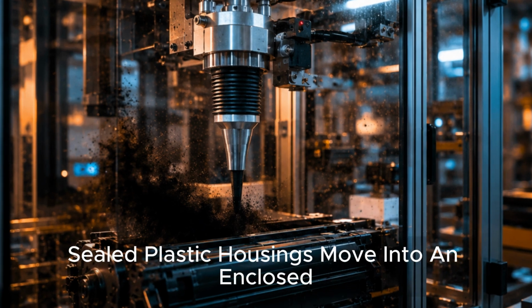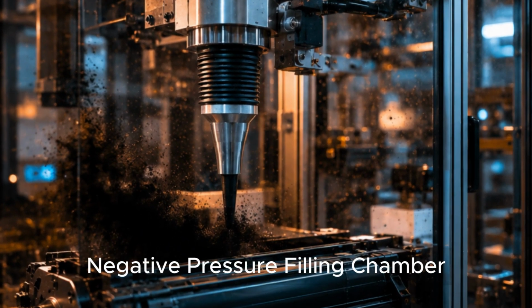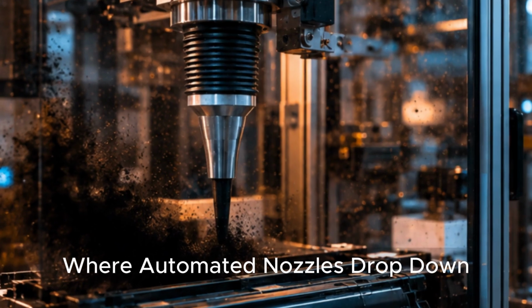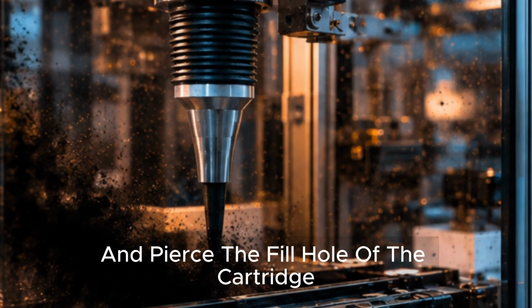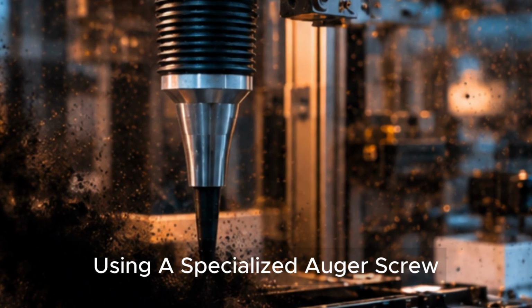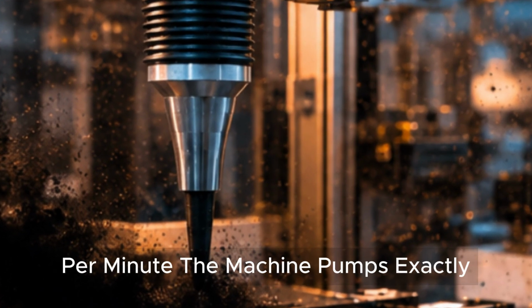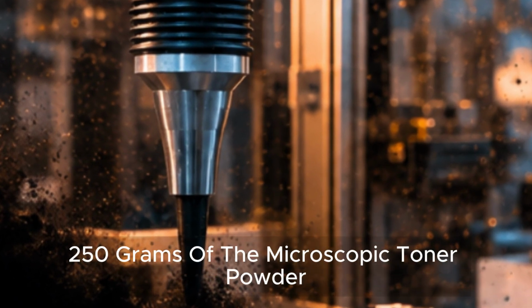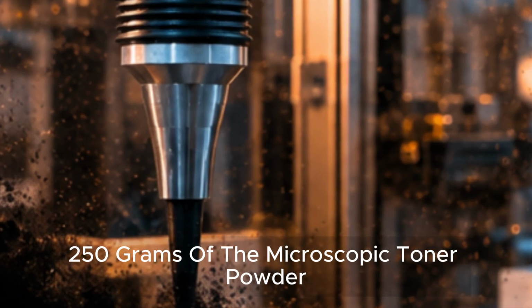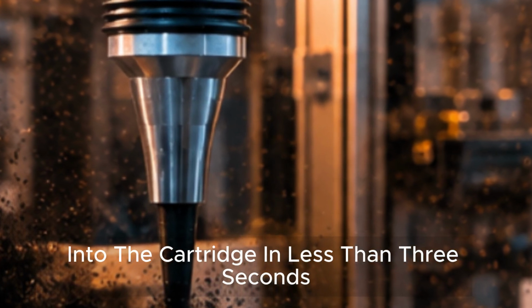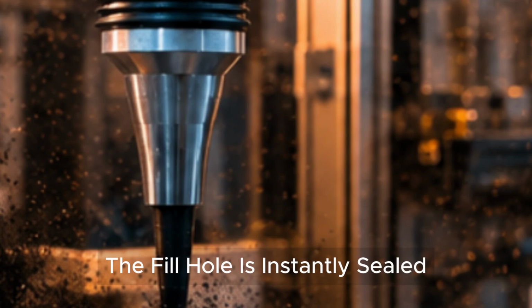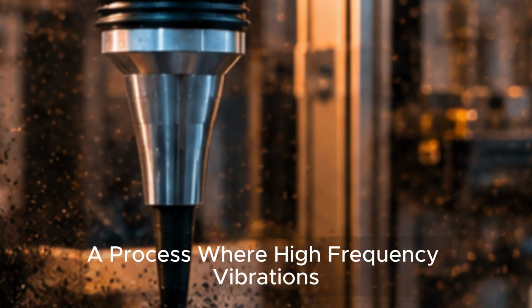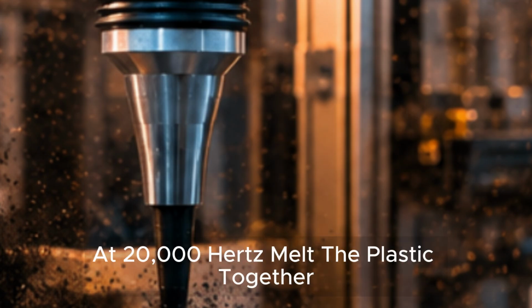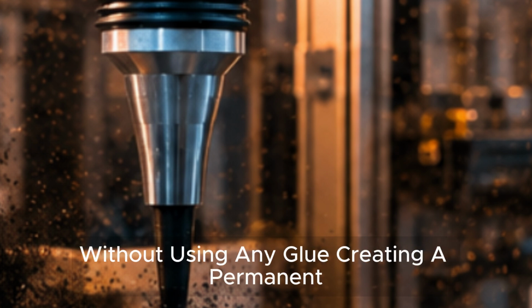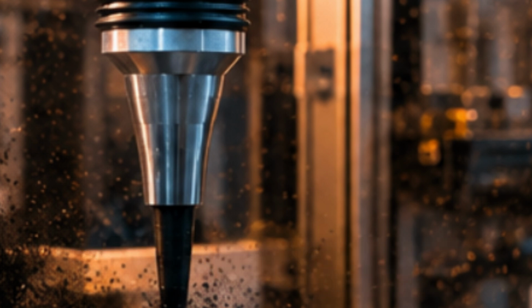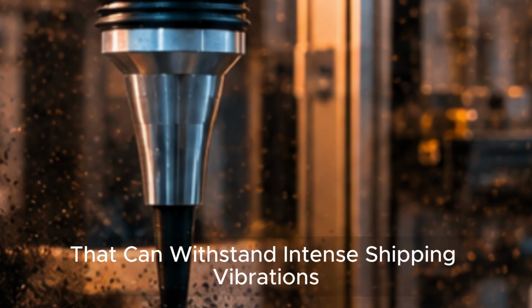The empty, sealed plastic housings move into an enclosed, negative-pressure filling chamber where automated nozzles drop down and pierce the fill hole of the cartridge. Using a specialized auger screw spinning at 150 revolutions per minute, the machine pumps exactly 250 grams of the microscopic toner powder into the cartridge in less than 3 seconds. The fill hole is instantly sealed using ultrasonic welding, a process where high-frequency vibrations at 20,000 hertz melt the plastic together without using any glue, creating a permanent, leak-proof bond that can withstand intense shipping vibrations.